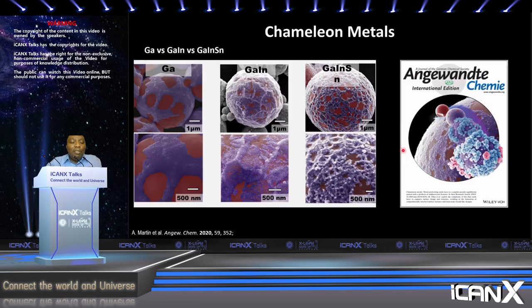But then based on what we observed with the first layer, we went back and looked at gallium, a unary metal, a binary, and a ternary, focusing on just that first layer, and we can see that the composition affects the kind of morphology you get on that first layer. And we believe this is due to the fractures that are occurring on the oxide and a composition due to cohesive energy density associated with the miscibility of the components that you have in the alloy.